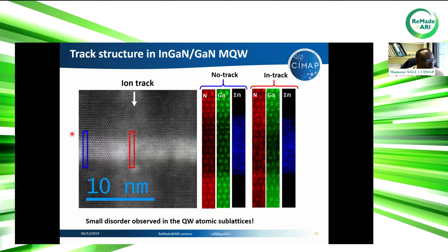We have also performed EELS analysis. This is atomic EELS mapping inside a track and outside a track. Outside the track, you can see here that the mapping is clear. You can see the atomic columns of all the elements. When we go inside the track, we can still see the atomic columns, but the map is a little bit blurry. But we cannot see a clustering of defects. This means that we don't have too many defects created by the swift ion in the quantum well. And this is, in fact, a good point.